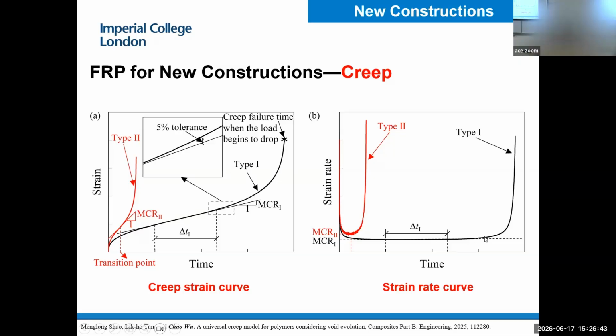This is the strain rate under creep loading. At the moment in the literature there are different models to describe creep behavior. We have models which can tell at what time the material will fail under creep loading, and also models which describe the creep rate in the second stage. However, there is no model available which can tell the time for the three stages, like when it enters the second stage, when it enters the third stage. There's no model to predict those times.